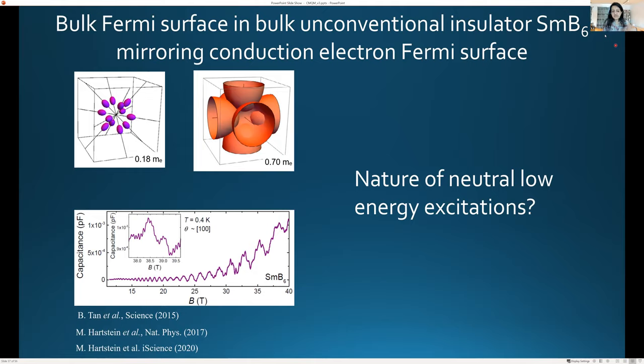So I think if one had a metal of some kind and you saw different frequencies with different techniques, one would conclude that different aspects of the Fermi surface were being picked up by different techniques. For instance, differences in curvature, differences in the mass of certain components. In this particular case, it does seem a bit surprising that there's no evidence for quantum oscillations in the electrical resistivity. I don't know if that is part of the strangeness of this material, but it is true that we're working with a very insulating material. So we shouldn't be overly surprised that the quantum oscillations in this material may have some other reason for not showing up in the electrical resistivity.